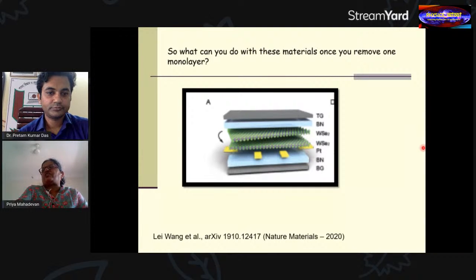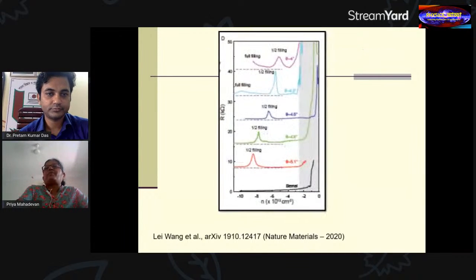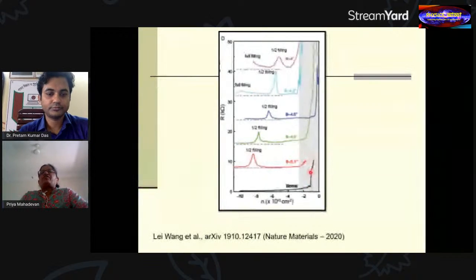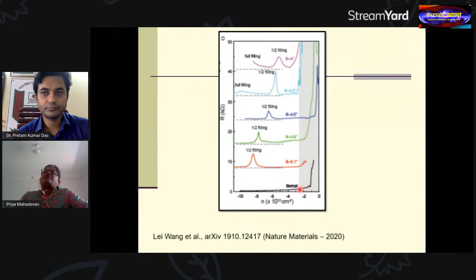Now, tungsten is an atom which is just below the molybdenum atom in the periodic table. So nothing should change. It should have very similar semiconducting properties. However, what they saw was something very, very strange. So this lowest plot over here corresponds to the simple semiconductor, and what is plotted over here is the resistivity as a function of hole doping.